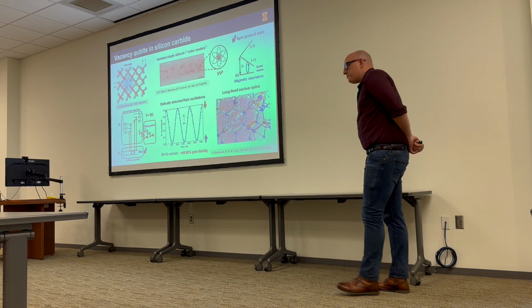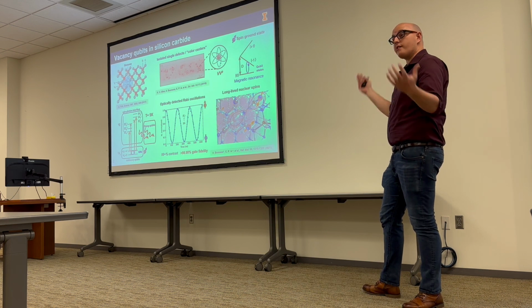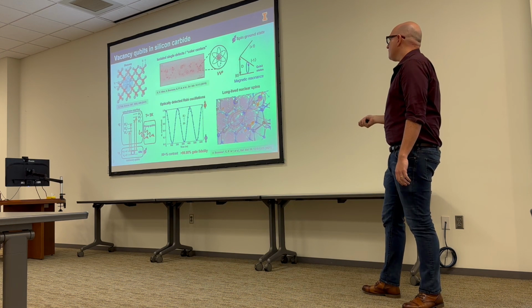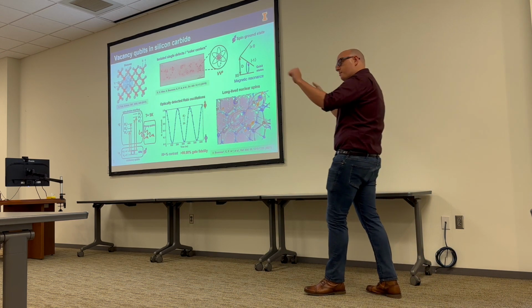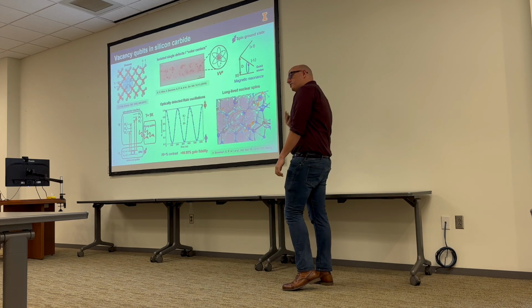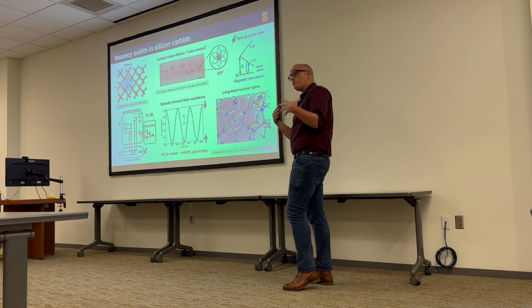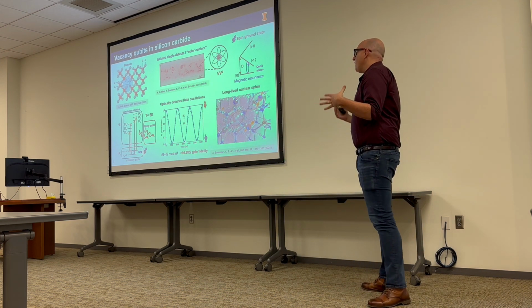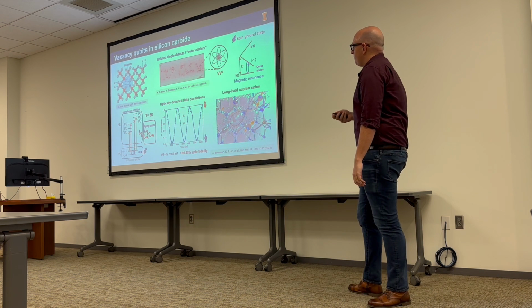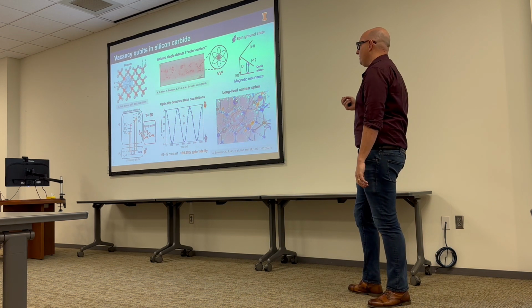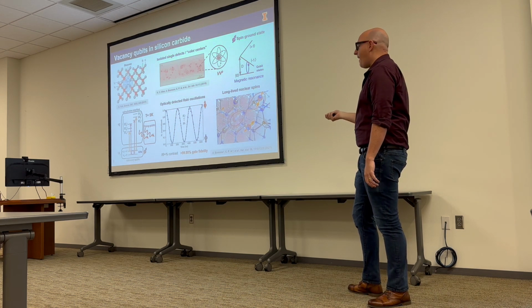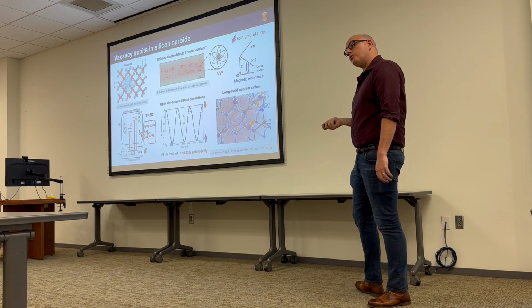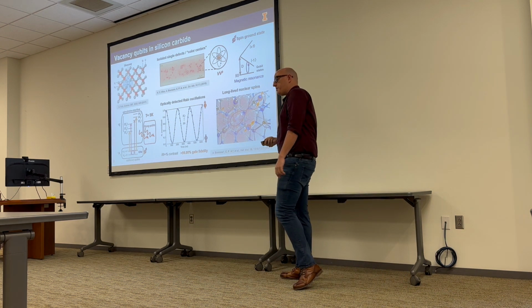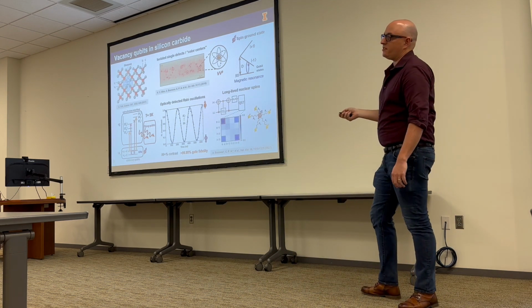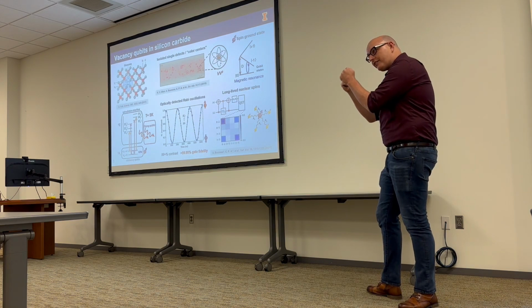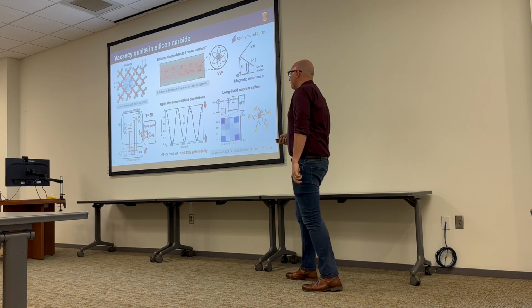And one of the other benefits of being in this solid state platform is we're surrounded by a bunch of other atoms. That's a blessing and a curse. Some of those atoms have a nuclear magnetic moment. They're like little bar magnets. But the problem is they fluctuate all over the place. They cause noise, but those little bar magnets can also be other two-level systems that we can couple to and use as quantum memories. And we like this because nuclear spins are basically the longest lived quantum object that's known to science. Their lifetimes can be hours, minutes, days. And so having them immediately accessible, and we can think about magnetically coupling to those nuclear spins, what we've actually been able to do is entangle a single electron and a single nuclear spin that are locally in this lattice, and think about using that as a quantum memory.